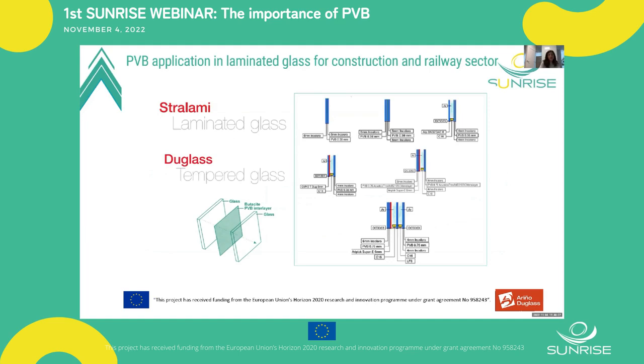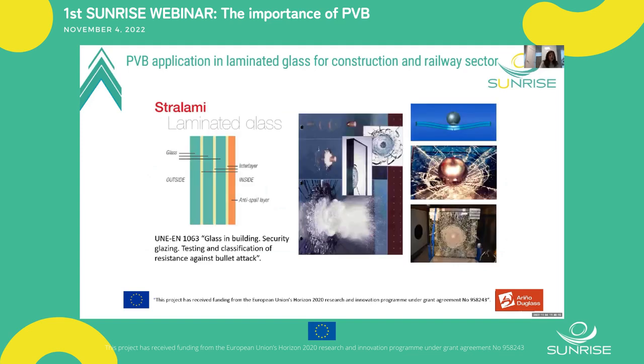In this slide, we can see different types of glazing with laminated glass, depending on the application. Another characteristic of laminated glass, in this case always with tempered glass, is protection against the risk of physical accidents. The high elasticity of PVB makes it highly resistant to impact. If a break occurs, the little glass fragments remain attached to the material and the structure remains intact. This is safe for people nearby, and it makes it difficult for anyone or anything to get through. This composition has passed the resistance test of different firearms according to the standards in accredited laboratories.